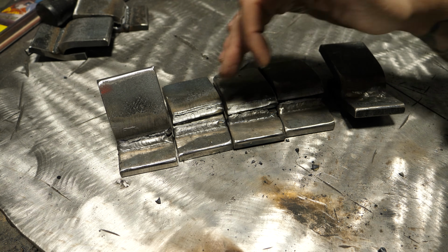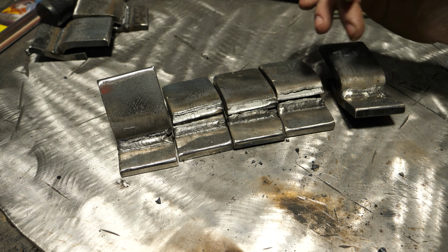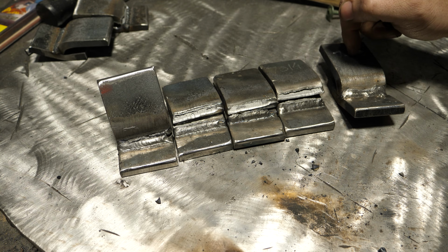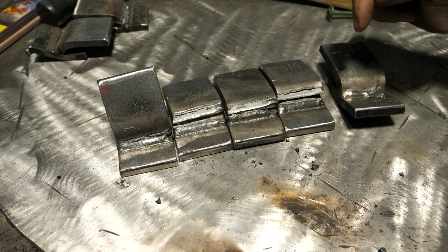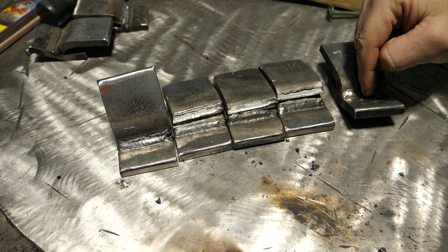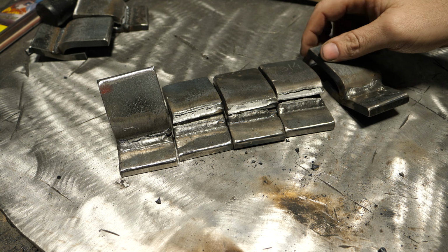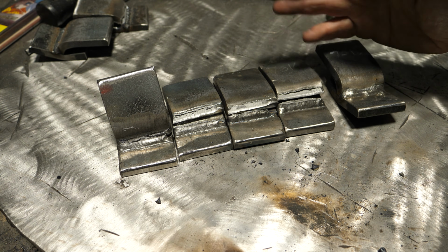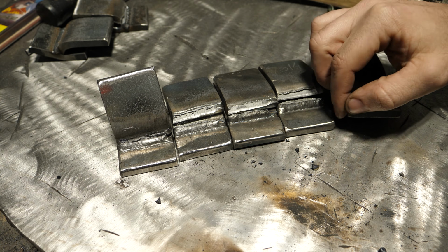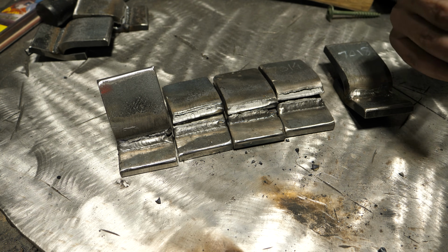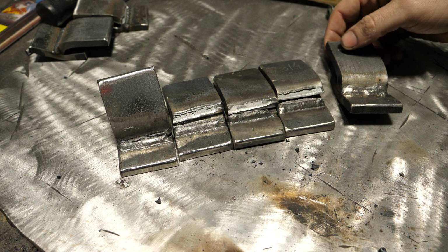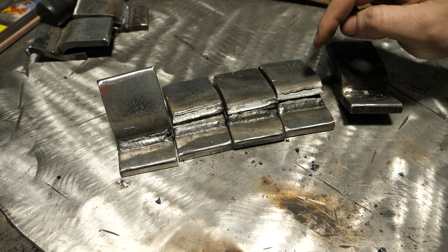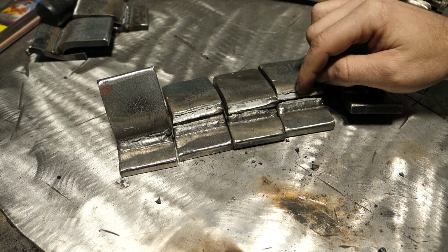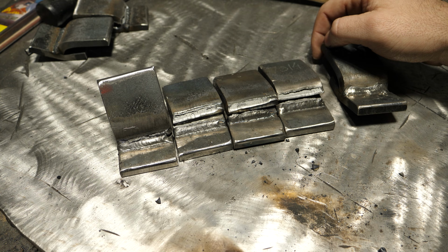And to have 4 of these fail, and I have yet to have one fail in 7018, one in dual shield. I did test a dual shield off camera. That did not fail. An ER70 MIG did not fail, and presumably TIG isn't going to fail either. I haven't tested it. But that, without a shadow of doubt, as far as I'm concerned, proves that 7018 in tension is a stronger weld than 7014.